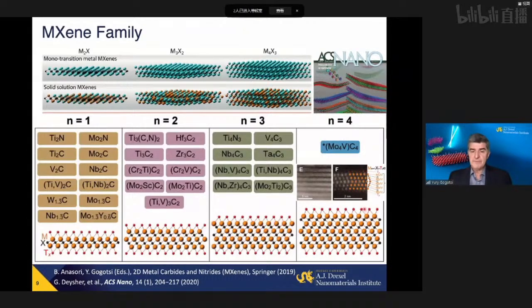About a year ago, we published this paper in ACS Nano, showing that we can make materials with actually 5 layers of transition metal bonded by 4 layers of carbon, molybdenum vanadium carbide, Mo4VC4, a thicker structure. The transition metal inner layers give electronic properties, electronic conductivity. Free electrons of the transition metal provide this conductivity. And the outer layer, terminated by oxygen or OH, gives this reversible redox.